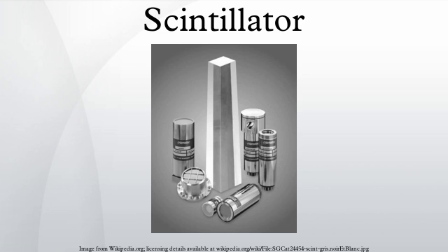Bases. The most common bases are the aromatic plastics, polymers with aromatic rings as pendant groups along the polymer backbone, amongst which polyvinyltoluene and polystyrene are the most prominent. While the base does fluoresce in the presence of ionizing radiation, its low yield and negligible transparency to its own emission make the use of fluors necessary in the construction of a practical scintillator.